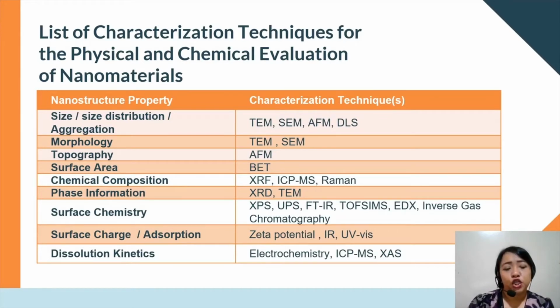For chemical composition, we can use the XRF, X-ray fluorescence, ICP-MS, and the Raman spectroscopy. For phase information, we can use XRD and TEM. For surface chemistry, we have XPS, UPS, FTIR, TOF-SIMS, EDX, and inverse gas chromatography.